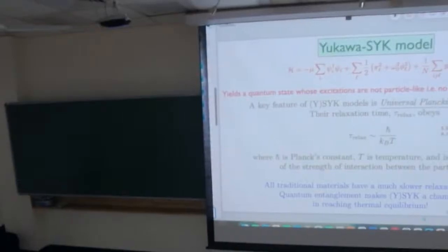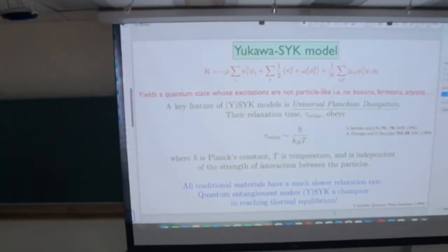All right, so that's very exciting that it has Planckian relaxation, but Esterlis and Schmalian pointed out something else. It has a zero temperature entropy, which cuprates definitely don't have. So some things work, but not most other things. And it's in 0 dimensions. So what do we do? Well, basically what works is you just take this model and make it realistic. You take all the three terms and you make them realistic.